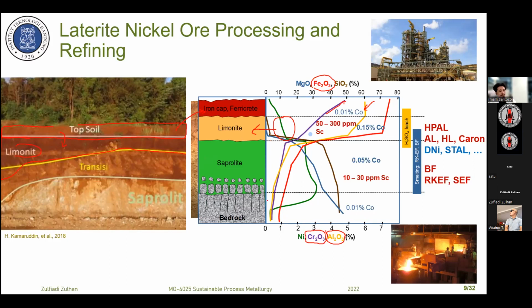And less magnesia, also less than 5%. In some cases it could be around 6%, and also less silica content, the brown color here. Less magnesia, less silica. We don't pay much attention to this kind of ore, because it will be processed via hydrometallurgy. It's a common technique today. It uses HPAL, for example, to process the limonite ore to get the product MHP, which can then be converted into nickel sulfate. The other processes could be atmospheric leaching, heap leach, Caron, DNI, and also STAL, which is currently being developed in Indonesia.